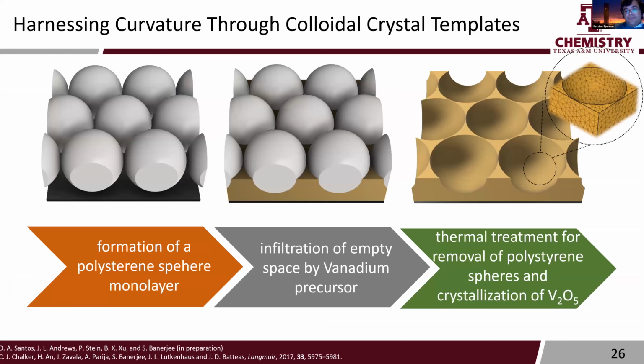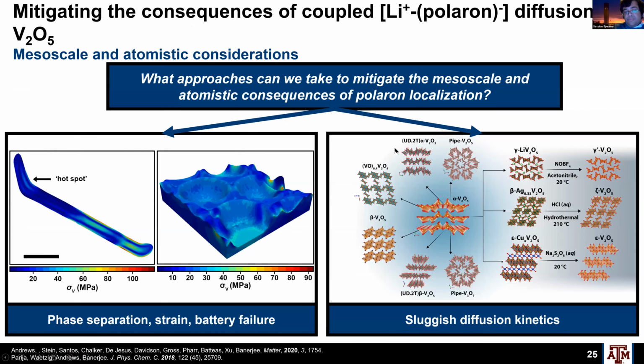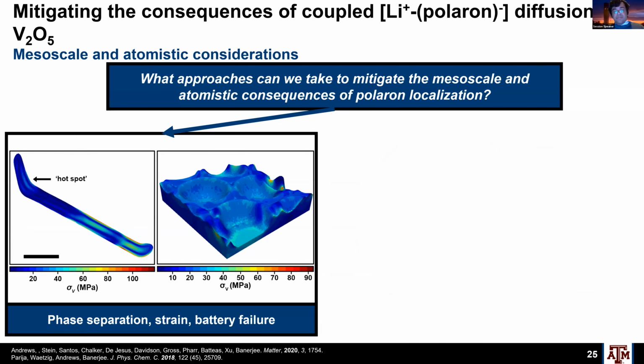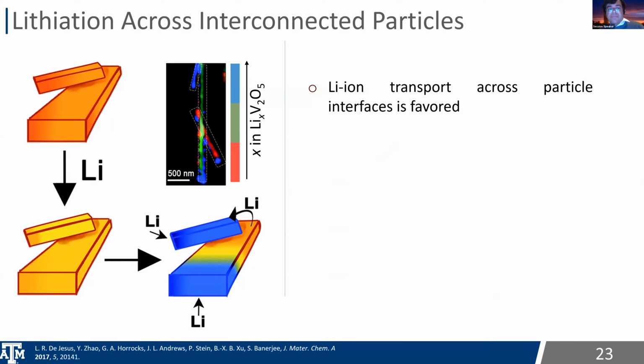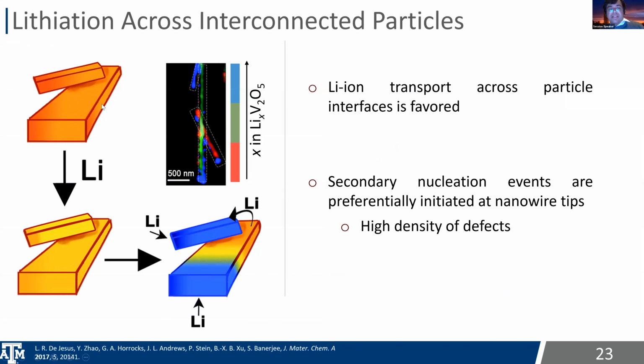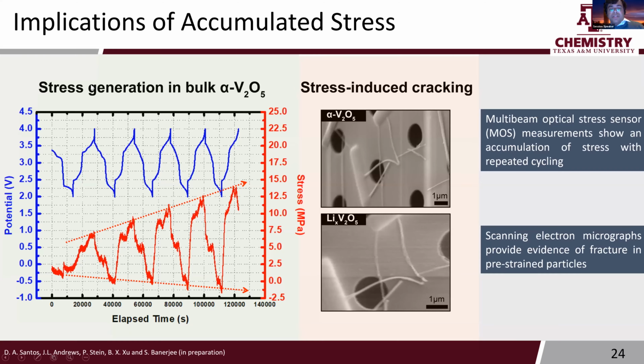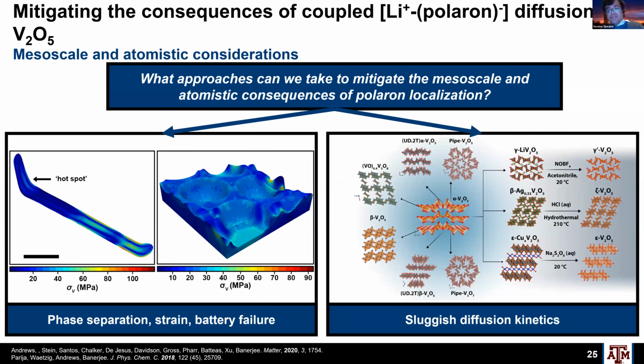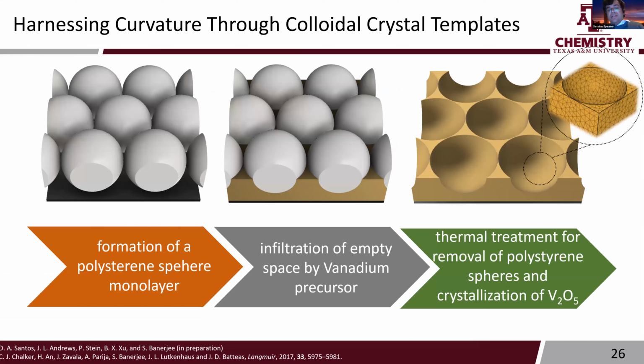Okay, so one way we've gone about this is harnessing curvature. Okay, so we saw how curvature, both in this particle, this is an irreversibly deformed bent wire, as well as prior examples here where we've got structures that have been elastically bent. Okay, so curvature can clearly affect diffusion pathways. So what if we have continuous curvature in these systems? So we made these inverse opal structures where we form a polystyrene sphere monolayer. We infiltrate with the precursor, and then we remove it, and we can get these structures.